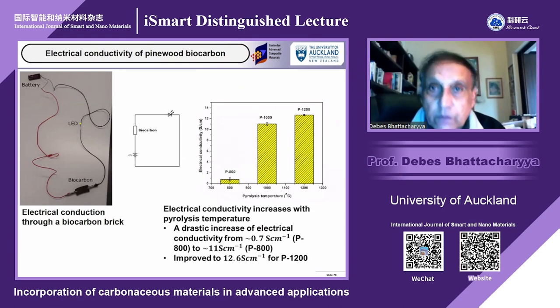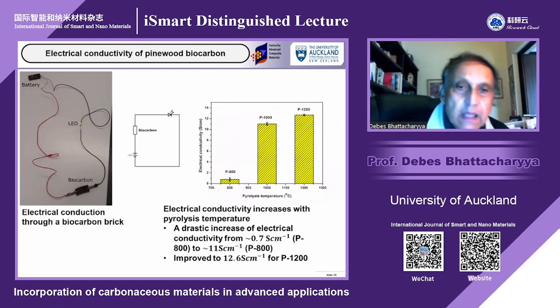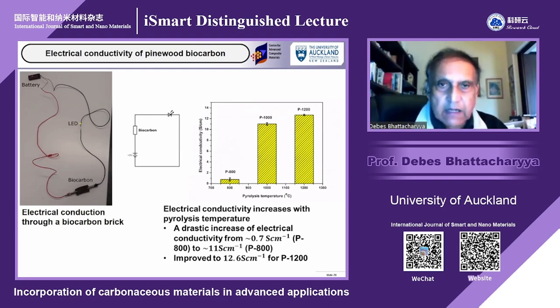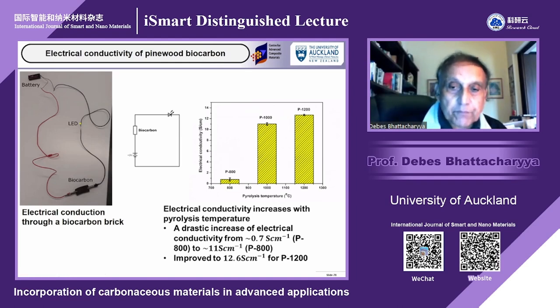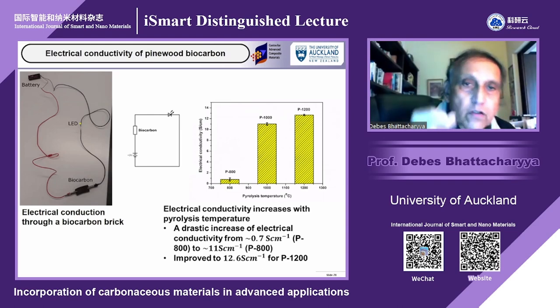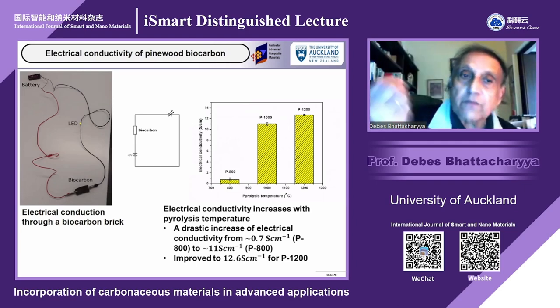Also, we use pine wood because that's the available material in New Zealand. And you can take a chunk of pine wood and really make it conducting by applying the proper temperature and environment. We did that, and the conductivity drastically increased. We could go from 0.7 Siemens per centimeter to 11 Siemens per centimeter by changing the pyrolysis temperature. We are a bit sensitive there, so I'm not giving all the details, but it improved to 12.6 Siemens per centimeter at about 1200 degrees C. So it is very sensitive to temperature. As I said, from a block of pine wood we can create an electrode. We have gone that far.